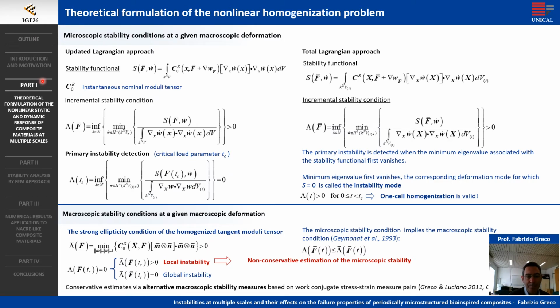The stability condition at a given macroscopic deformation is studied here based on the positivity condition for the stability functional S for every incremental deformation satisfying the periodic boundary condition. The primary instability is detected when the minimum eigenvalue associated with the stability functional first vanishes. It is important to note that a classical macroscopic stability analysis based on the strong ellipticity of the homogenized moduli tensor is not usable in general, since it provides a non-conservative estimation of the primary instability load when the instability mode is local in nature.